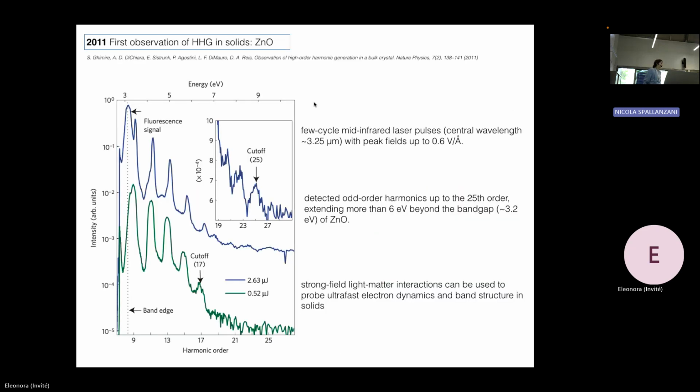And finally, this is for the solid in 2011. That was the first observation of HHG in solid. This is the reference article I show you. It was done on zinc oxide, and so there was this measurement of HHG, the strong-field process. And you can see these peaks that are all these harmonics.